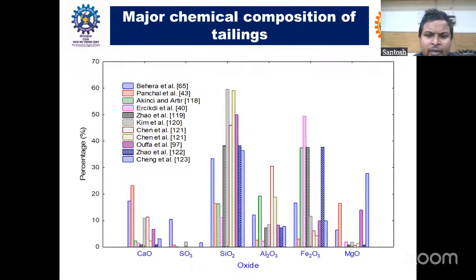And what is the major chemical composition of various tailings? What we studied, this is Behra et al. This is a lead zinc mill tailings. Generally, the tailings are composed of silica, SiO2, then Al2O3, Fe2O3, some amount of MgO, CaO, and also SO3. So there is a role of the chemical composition on the backfill strength. If we have higher proportion of CaO, SiO2, and MgO and others, the strength is better. Whereas if you have higher proportion of SO3, it may create some negative impact on the strength in the long run.